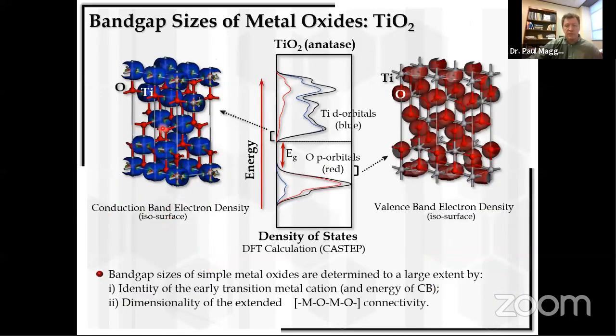So here's a summary for TiO2. That gives an important lesson. If you're going to try to tune the electronic structure of these materials, how you can do it is by shifting the conduction band up and down, but you really have no opportunity to shift the valence band up and down.